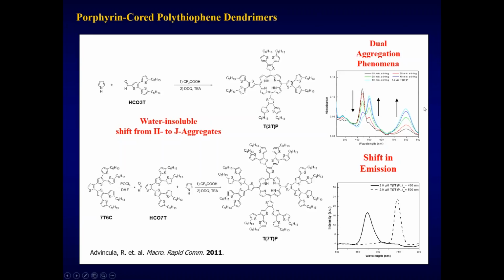Unfortunately, I will not be able to show you some of the AFM images here, except that we focus in particular on the energy transfer properties as well as their complexation, as shown by this fluorescence spectra, where the self-quenching mechanism, or the stacking rather, of this polythiophene complex has resulted in quenching or relaxation of their fluorescence behavior as shown here. So this is what we call an indirect method of characterizing aggregation.